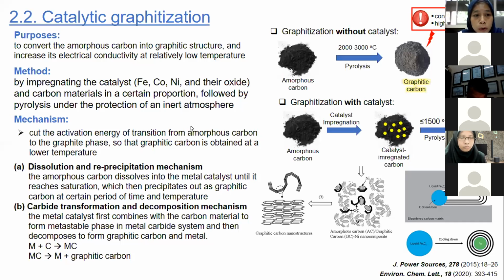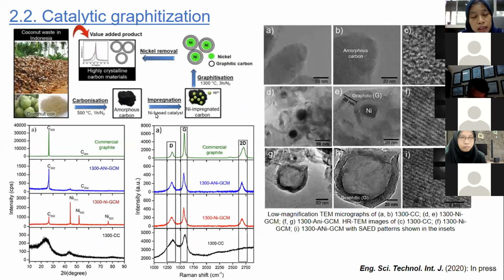We obtained the graphitic carbon from coconut coir or coconut fiber. This is the route of our experiment. First carbonize the coconut fiber at 500 degrees Celsius and then impregnate it with the nickel-based catalyst, and the graphitization process is at a relatively low temperature of 1,300 degrees Celsius. And after the acid treatment, we can obtain the graphitic carbon.